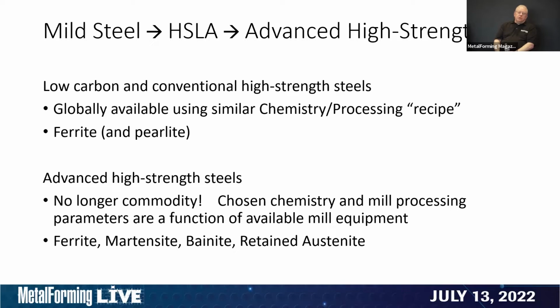The microstructure of mild steels and even conventional high strength steels is primarily a phase that's called ferrite. In the advanced high strength steels, we've got ferrite for sure, but also combinations of other phases: martensite, bainite, and retained austenite.